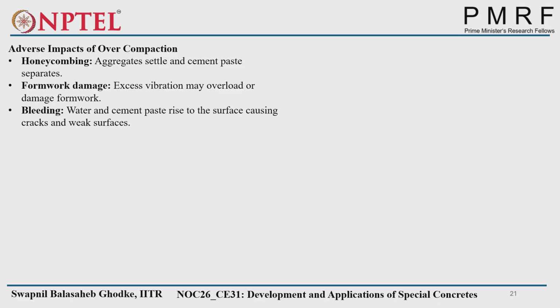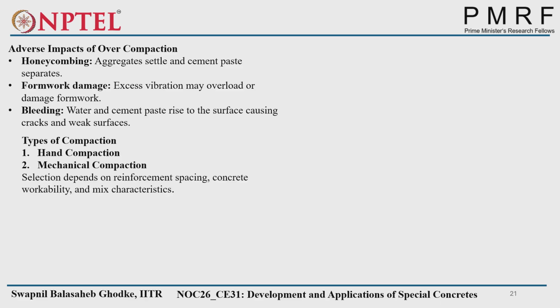Other adverse effects are honeycombing and formwork damage, because it creates higher pressure. With more compaction, the pressure of the concrete will come onto the adjacent formwork. Bleeding, water and cement paste rise to the surface, causing cracks and weak surfaces. These are all about the compaction.